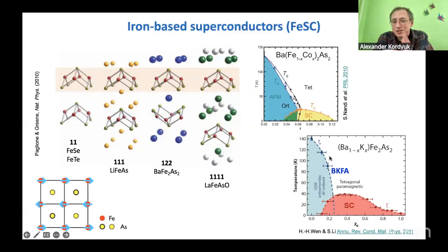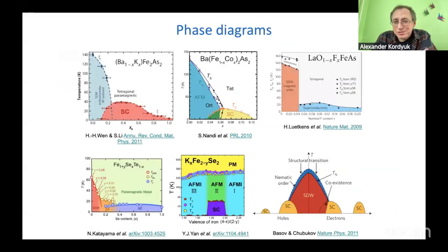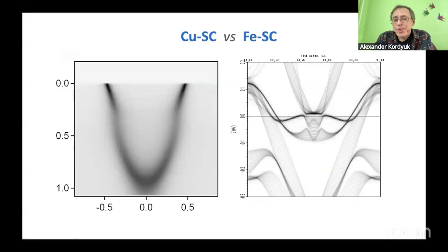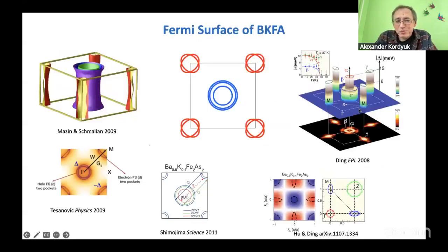In cuprates, this is antiferromagnetic phase, but insulator. Here it is antiferromagnetic, but metal. And there is some ordering, and this ordering was also similar. But comparing to cuprates, it has much more complicated band structure. Instead of one band or two bands in two-layer cuprates, it has 5 bands, and actually 5 Fermi surfaces.